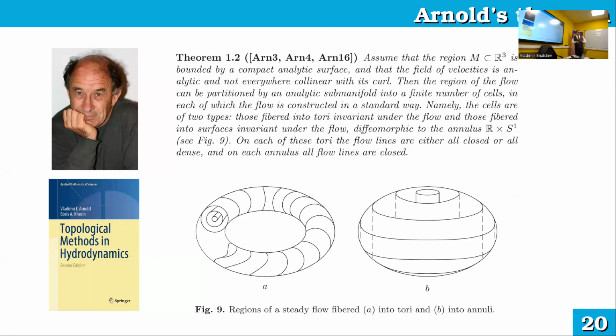Basically, it states that if you have some volume, and inside this volume you have divergence-free incompressible fluid, the space will be partitioned into toroidal or cylindrical flows. And that's what we see in our case, in full agreement with Arnold's theorem. Our nanoparticle also partitioned into tori or vortices, which are cylindrical cells, and they are not overlapping at all. They have distinct boundaries, and they're also separated by Bloch points.